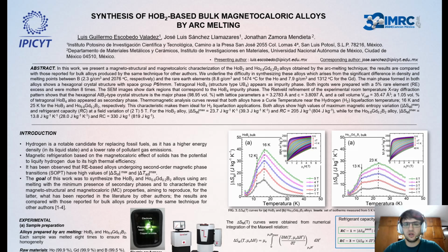It is important to note the difficulty in synthesizing these alloys due to the differences in melting points and densities of the rare earth elements and boron, as well as the presence of the antiferromagnetic phase holmium tetraboride. This is reflected in the fact that 8 meltings were necessary in both cases to achieve homogenization. The magnetocaloric properties here obtained are outstanding, as our results are comparable to those reported in the literature.